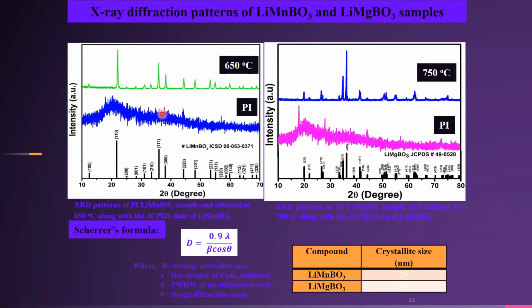So the XRD pattern of the polymeric intermediate sample of lithium manganese borate, and another one calcinated at 650 degrees centigrade, along with the JCPDS data of lithium manganese borate sample. The polymeric intermediate sample of lithium manganese borate shows a peak-free X-ray diffraction pattern, which confirms the formation of the amorphous phase. And for the sample obtained at 650 degrees centigrade, the X-ray diffraction peaks are compared with the JCPDS data file of lithium manganese borate sample, confirming the formation of pure hexagonal phase of lithium manganese borate.